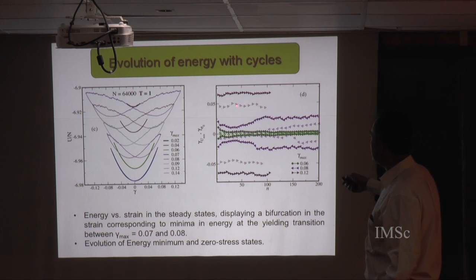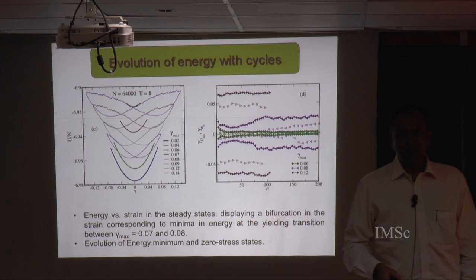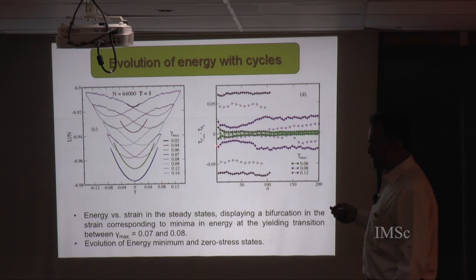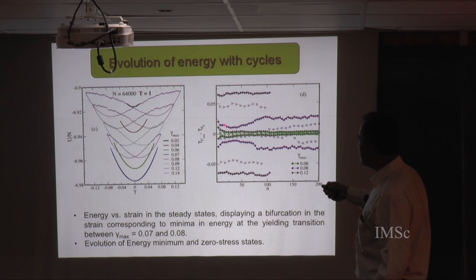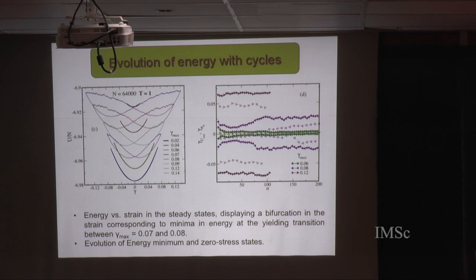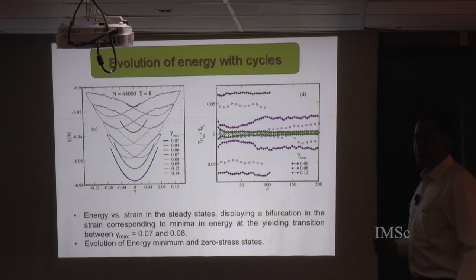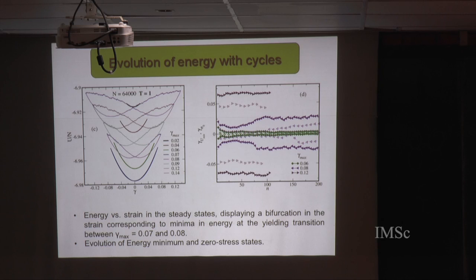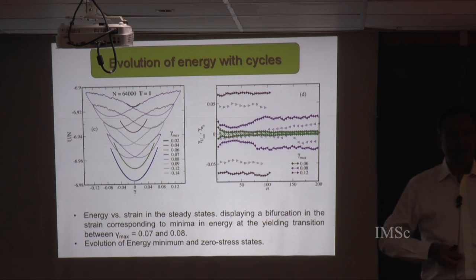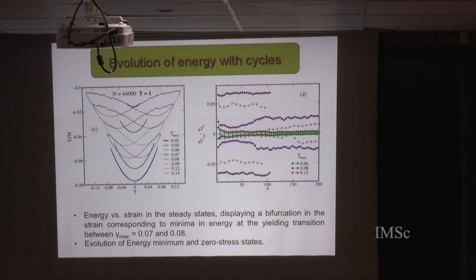Above the yielding point, the lowest energy strain value is something finite, but right around the transition you see something interesting: there's an initial decrease of the strain value before it kicks off and goes to larger values. So this is a case where the system initially attempts to find some local equilibrium, but is not able to, and then escapes to a yielded state with this larger strain value at the minimum. This is of relevance to how we characterize the yielding transition. There's some recent work I'll mention later if anybody asks, which can be interrogated with data like this.